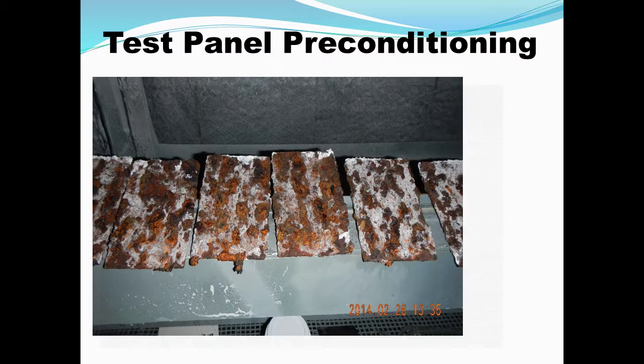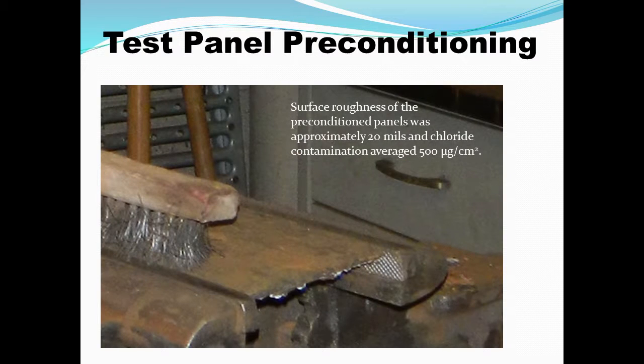There's a lot. After 2,000 hours, they were all cleaned by wire brush, just to get a constant cleanliness on them. As you can see here, the underside of this panel has not been cleaned at this point. There are still the deposits, but the top side has been wire brushed. What we found after wire brushing these 100 or so samples is that there was pitting in the 20 mil range, sometimes more. So it's a moderately rough surface, maybe not as rough as some of the field conditions, but in that range.